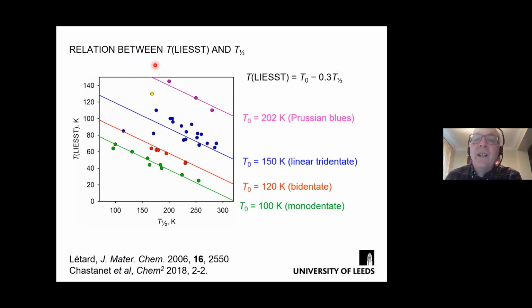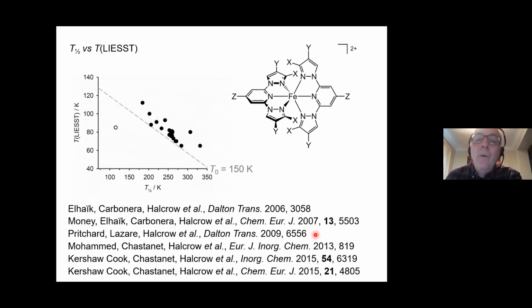And these are three-dimensional inorganic lattices. And basically, as your molecule or your ion center becomes more rigid, then the kinetic relaxation at low temperature becomes more difficult, and T(LIESST) goes up as your molecule becomes more rigid. That's the basic message from this graph. So these are compounds that we've measured, always with the Bordeaux group, I should say. They have done these measurements for us. This is the correlation line that they originally proposed. I think actually this line looks a little bit better for our data, but you know, the basic